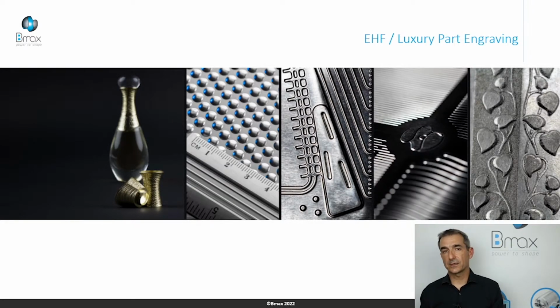If we analyze the takt time, one part is formed in 18 seconds, and we can imagine if the conventional process consists of machining, 1 or 2 hours would be required to form the same detail. So thanks to EHF and the Bmax solution, we can reduce the scrap, we can reduce the lead time for production, and we can reduce the material consumption. The next movie shows the real automatic system developed for this production, but it's adapted to a Bmax goodie. It's a USB memory stick.